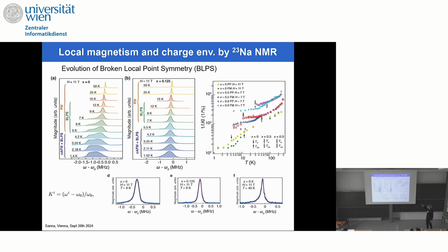And so we can very nicely measure this splitting temperature, which is the temperature below which the spectrum becomes distorted. Okay, very good. We can also do very nice fitting, simulate everything, analyze everything, and say that this is related to this broken local point symmetry condition, which was already observed in the single crystal for the sodium compound, and here is the same in the powder sample.